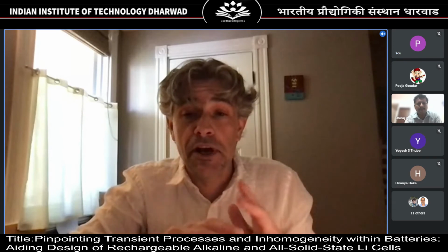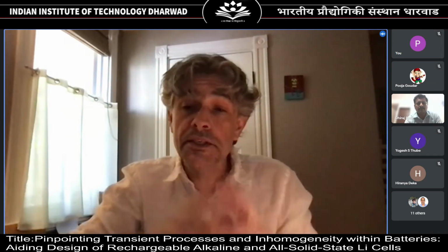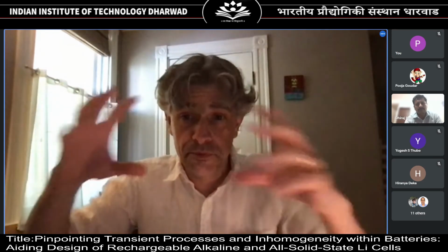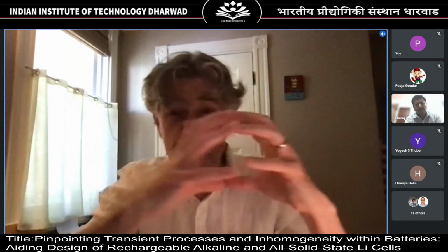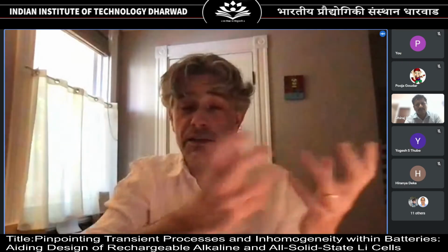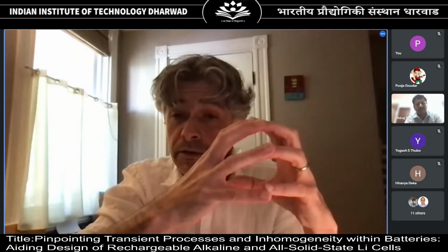Fracture mechanics. Now let me talk about fracture mechanics, which is something I know very little about because I'm not a mechanical engineer. I'm a chemical engineer. But when the battery is cycling, say a lithium-ion battery, this cathode material is particles, and those particles are in a porous electrode. Now imagine a particle. That particle is also made up of particles. So it is an agglomeration of crystallites. Those crystallites could have grain boundaries or they could be single crystal, but they are small crystallites of material, and they're all agglomerated together.